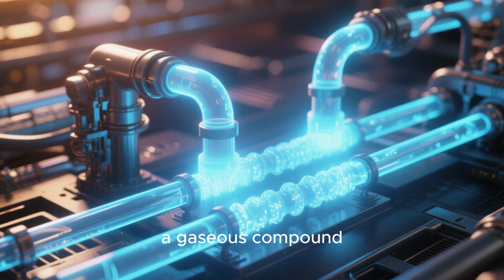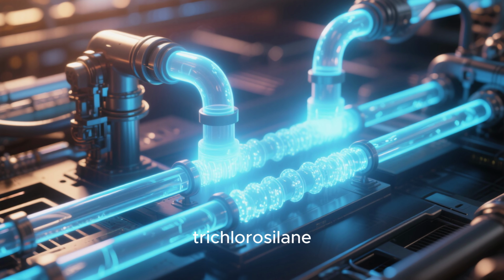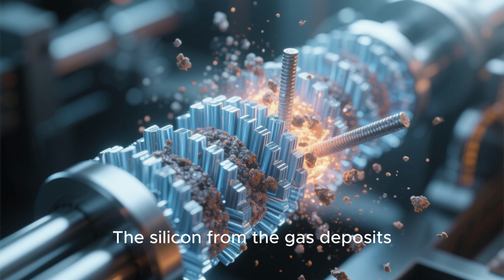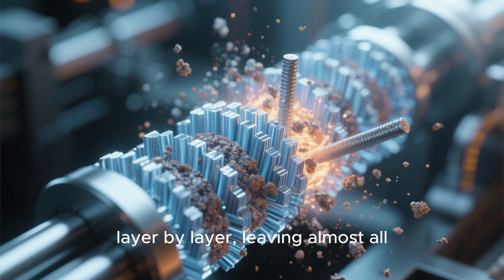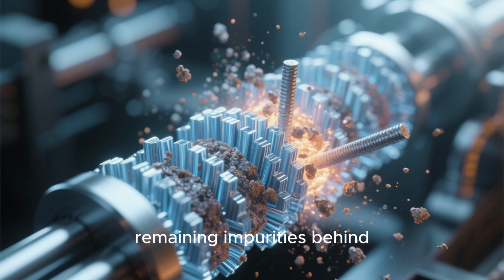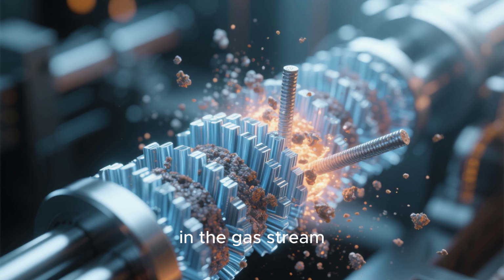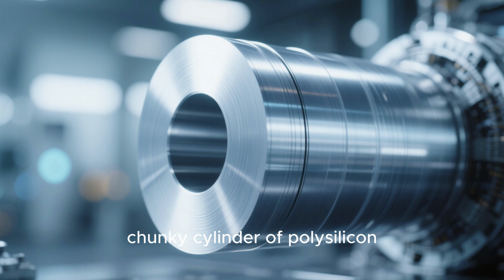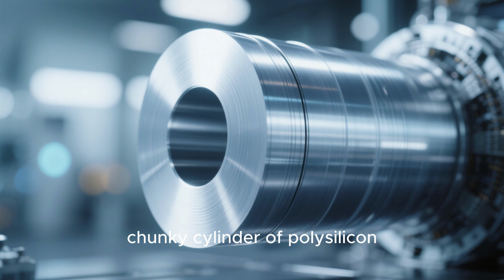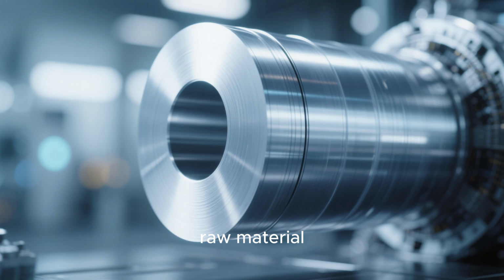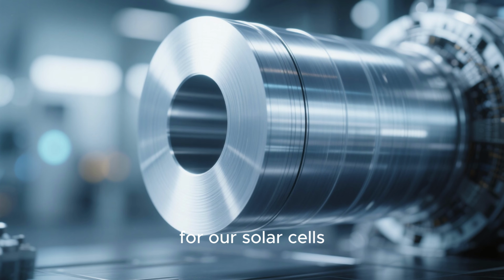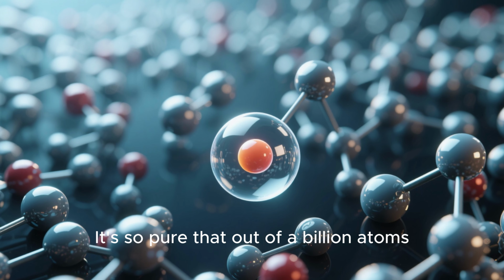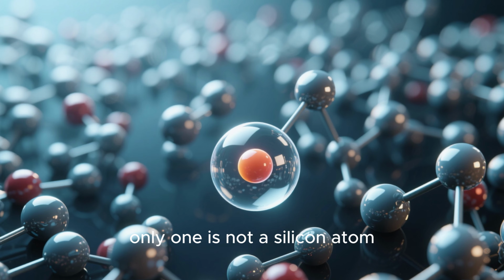It's converted into a gaseous compound called trichlorosilane. This gas is then flowed over heated ultra-pure silicon rods. The silicon from the gas deposits onto the rods layer by layer, leaving almost all remaining impurities behind in the gas stream. The result is a big, chunky cylinder of polysilicon, which is the ultra-pure raw material for our solar cells. It's so pure that out of 1 billion atoms, only one is not a silicon atom.